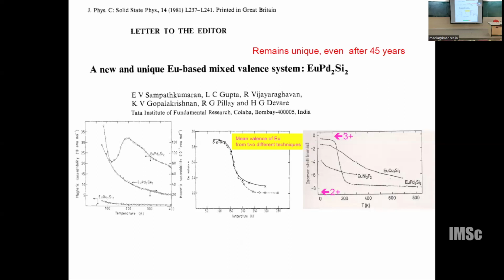So if you wanted to know the valency, you can determine it from these numbers, using the susceptibility of this compound and the susceptibility of trivalent and divalent systems. This is called the valence. You can see here it goes from almost 2+ to almost 3+ as a function of temperature. That means the electron goes out, you lose it from bonding, and it comes back. This is called fractional valence.